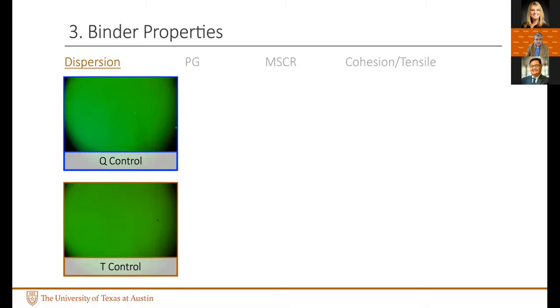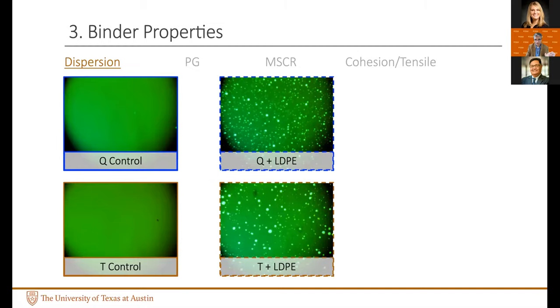So in terms of dispersion, you can see these are the two control binders. This is fluorescence microscopy, the two control binders. And once you add plastic, you will see that in both cases the plastic disperses, but it does not fully blend and does not become a homogeneous part of the asphalt binder. And all of this was done using a high shear blender. So even in that case, you would see small particulate additives left behind. So you can see how the polymer, the plastic LDPE, is being dispersed.